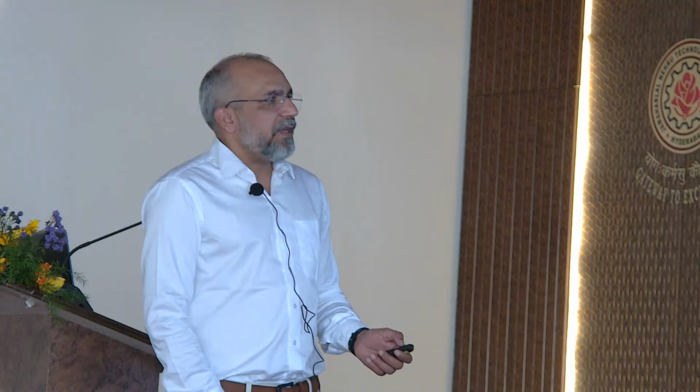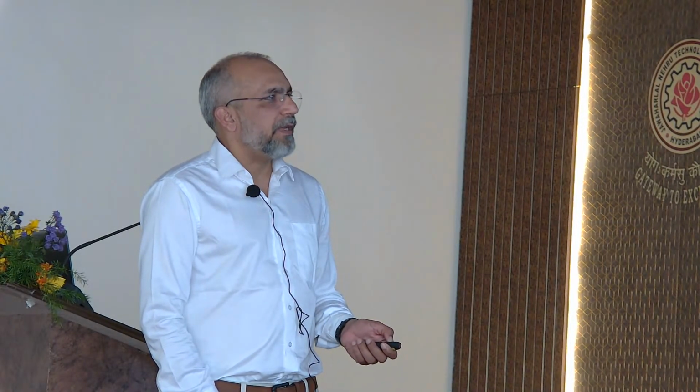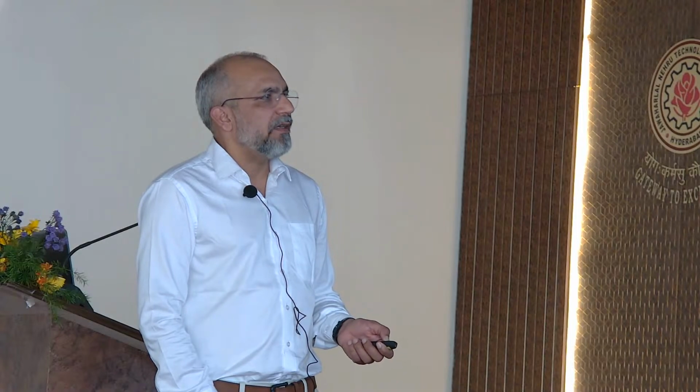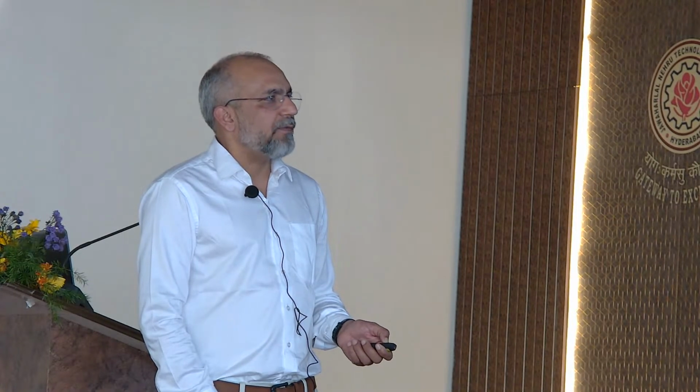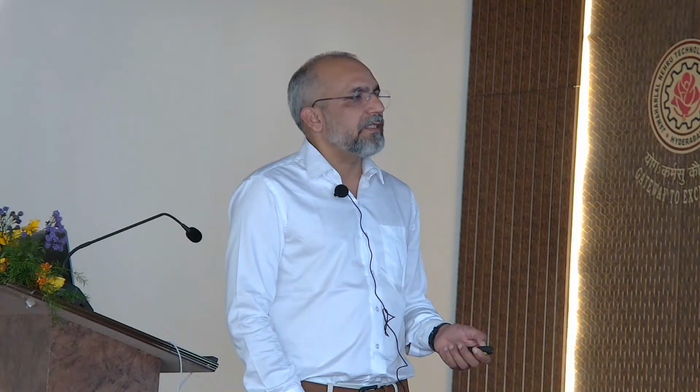The chemical method. Today you learned a little bit about chemical methods in the lab, and you synthesized zinc nanowires or nanoparticles, we don't know, but you did something, right? For the chemical method, it's a straightforward process. First you have precursor activation, then nucleation, and after nucleation you have two processes, either oriented attachment or atom-by-atom attachment. Through these two processes, finally, at the end of the day, you have a nanocluster or nanoparticle here.